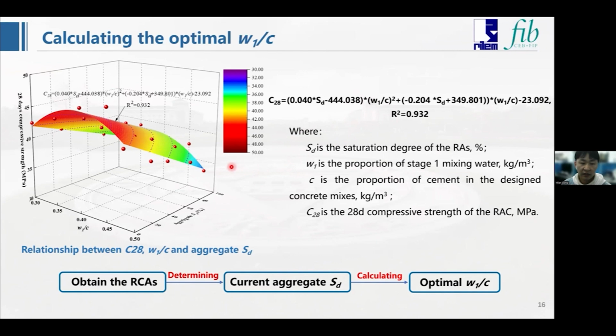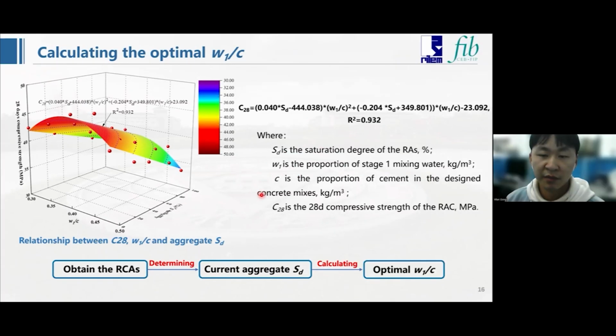When we obtain the recycled coarse aggregates, usually we will test their basic properties, such as water absorption and so on. So we can determine the current aggregate SD. And then we can use this formula to calculate the optimal water cement ratio corresponding to the current state of the aggregate. And that's how to determine the stage 1 mixing water.